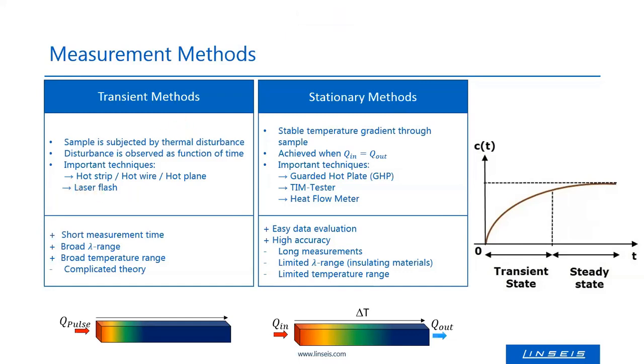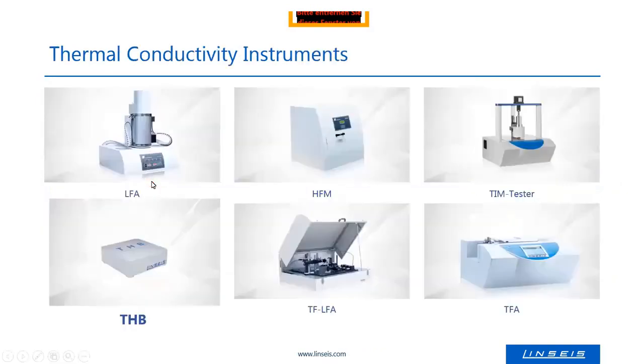The transient methods you can divide into, I would say, two different paths. One is the hot wire methods, and the other is the optical methods like laser flash or xenon flash. Both are transient methods, so you apply a pulse, a short pulse for laser flash, and measure the temperature increase. The hot wire techniques can also apply a short pulse, but also longer pulses, or the heat can be applied during the whole measurement, to measure the thermal conductivity.